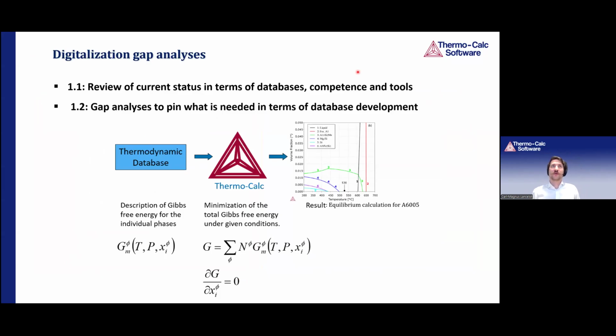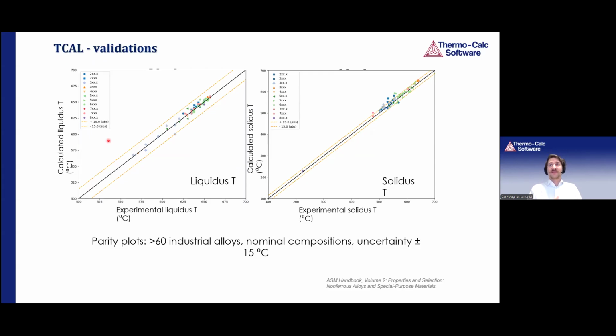And coming back to our work packages, so that was sort of a review of the current status and capabilities with our databases and the tools. And I want to talk a bit more about the next step, the gap analysis, which was mainly performed by my colleague Yang Yang, the database developer here. She's doing the validation work of the database, where she validates the database for many different multi-component alloys, calculated some important properties such as the solidus and the liquidus temperature for a large number of commercial alloys. These are both wrought and cast alloys, but we can see a pretty good agreement here within plus minus 15 degrees for the solidus and liquidus temperature, and we can also see which outliers are here in the predictions, and that can help identify areas where there could be improvements made.